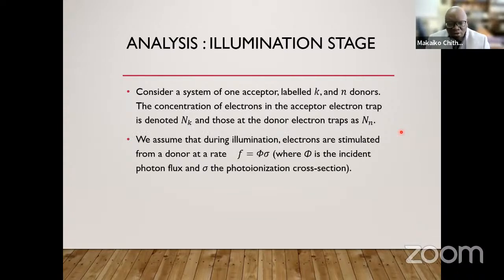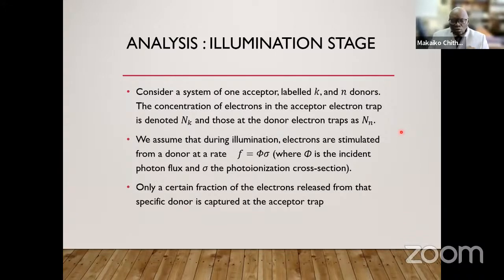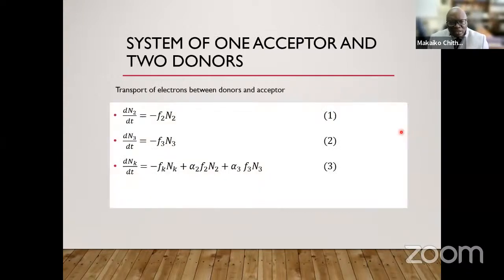As we illuminate our sample, electrons are stimulated from a donor at a rate F, which is phi multiplied by sigma, where phi is the incident photon flux and sigma is the photoionization cross section. Once electrons have been removed from a donor, or from a point defect, to the conduction band, only a portion of them will actually end up at the acceptor electron trap. So using these facts, one can write a set of very simple first order differential equations in this way.